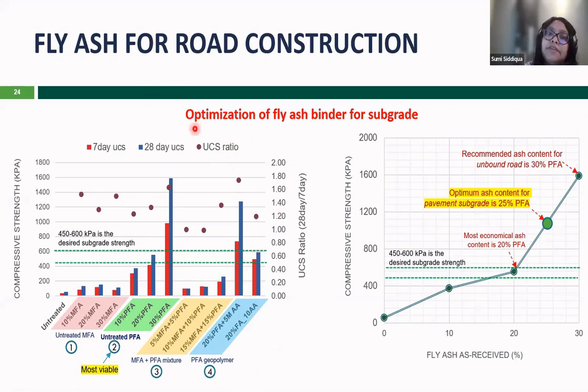So what we have used, we looked into the optimization of the fly ash binder for subgrade, and I will just go with that again: how the compressive strength over the period of time with respect to different combinations that we have shown here. For 7 days UCS, 28 days UCS, and the dotted points are UCS ratios between the 28 days to 7 days.